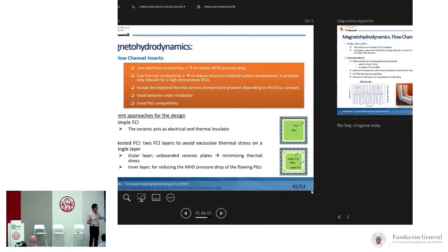We have another possibility, which is using 2 layers of flow channel insert. The outer layer, which is this one, is composed by different layers, unbonded ceramic plates to minimize the thermal stress, and the inner layer is to reduce the MHD pressure drop.